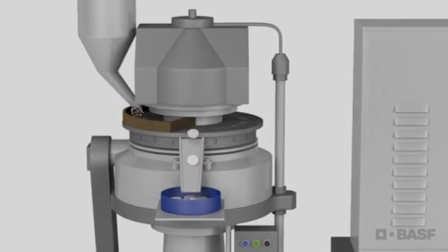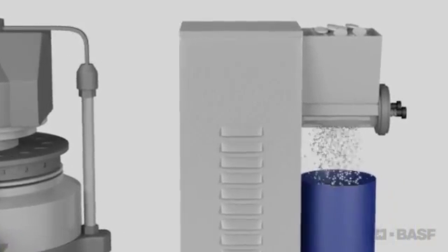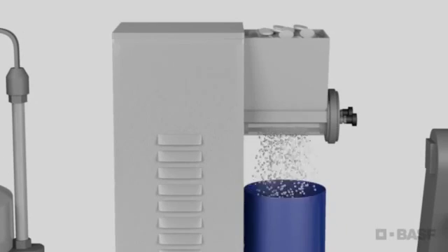The dry catalyst powder is usually pre-mixed with a lubricant, such as graphite, and is fed by a hopper into the wafer molds. The pre-densified wafers are fed into a granulator that pushes them through a screen which has a mesh size specifically defined for the material being processed.